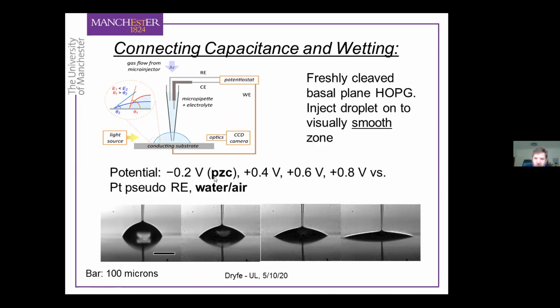This is only going up to about 1 volt positive of the PZC on this graphite surface. And the reason graphite is very good, you get this very strong electro-wetting of water on graphite, there's two reasons for it. One, because we have a macroscopically smooth surface, you can cleave basal plane graphite and get, if it's a good quality material, a basal plane that's free of large steps and defects, so the droplet doesn't get pinned as it expands. And the second reason is because graphite is relatively hydrophobic. So when we inject the water onto the graphite, the contact angle isn't too low. So we're already starting from a relatively high contact angle, which decreases as we do the electro-wetting experiment.